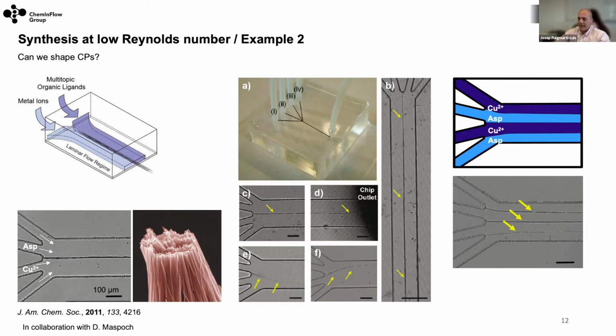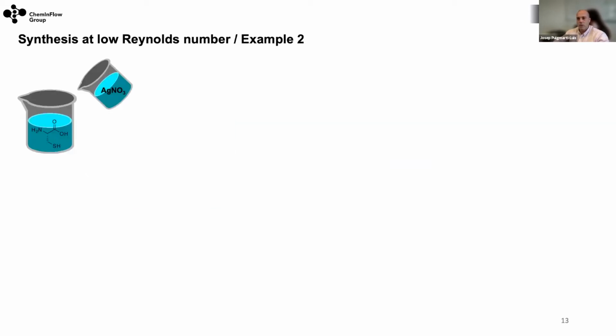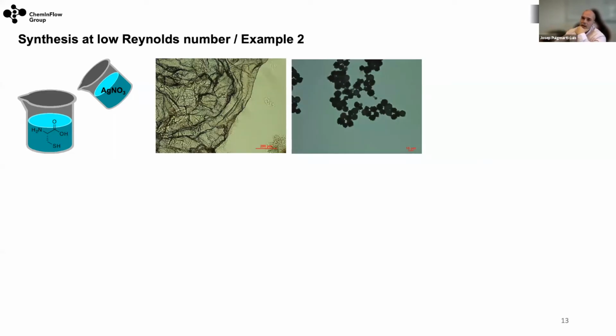But the question was then, can the shear stress on these fibers that are being generated also help to arrange other coordination polymers into fibers? This is actually what we were searching for in collaboration with the group of Professor Daniel Maspoch. We were looking for a coordination polymer that would not generate nanofibers. In this case, this silver cysteine coordination polymer generates a kind of membrane, and with time you have the formation of microcrystalline particles. So the idea is, okay, this is a good candidate. Let's see if we can generate some other type of morphology when we do the synthesis with microfluidics.